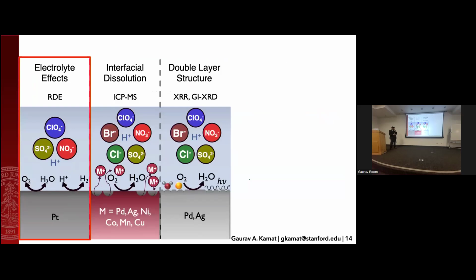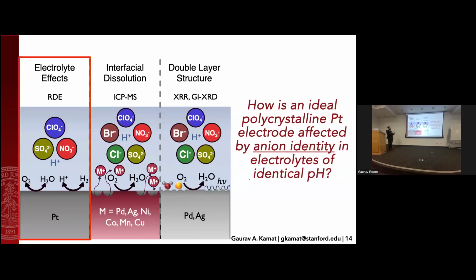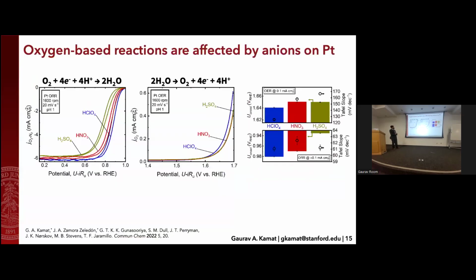So the first question that I had is looking at these electrolyte effects and just using a rotating disc electrode. How does an ideal polycrystalline platinum electrode actually get affected by anion identity in electrolytes of an identical pH? So here's what some of this data looks like. These are all on the same kind of platinum substrate, and they're biased to different potentials and in some cases different gaseous saturations to understand different components of the catalysis.